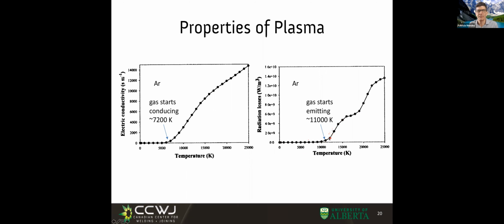10,000, 11,000 Kelvin. So when you see the arc, what you see is more or less the isotherm of 11,000 Kelvin. It's more or less what you see. However, electricity is also conducted a little bit outside that. Electricity is conducted in this range too, in which we don't see the light, but electricity is going on. You see that this curve has like these little squiggles.